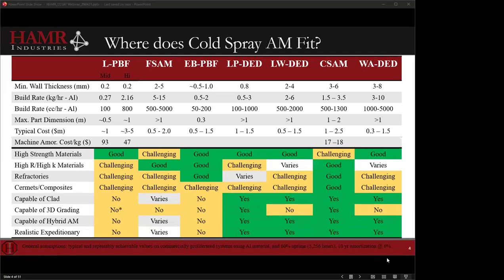And then the second half of the talk is going to be about more novel applications. So not only does cold spray have a role, we believe, in that additive tool belt, but we also believe that it's not only a specific tool, but a unique tool. And it can do a lot of other things that are either challenging or maybe not even possible with some of the other additive modalities. So when we look at the types of materials that it can process, when we look at doing things with refractories, with cermets and composites, and unique ways of operating, like cladding, 3D grading, functionally grading, hybrid AM, and expeditionary, that's when we see cold spray starts to really shine. And the only other modality that's really comparable to it is potentially powder DED, in terms of having this really large degree of flexibility.